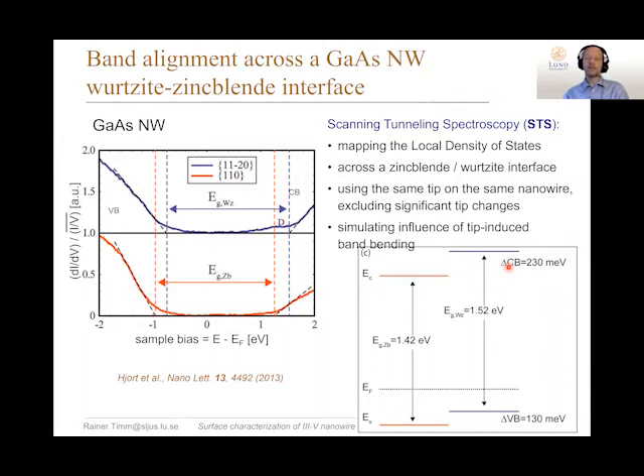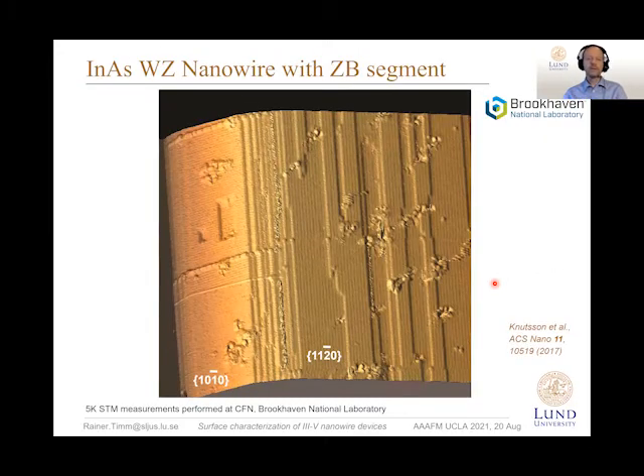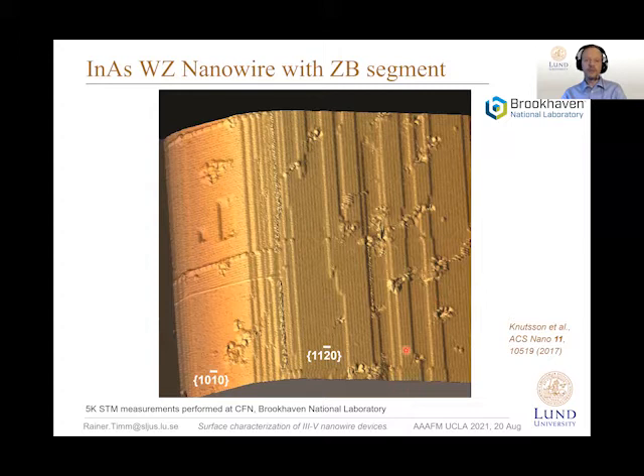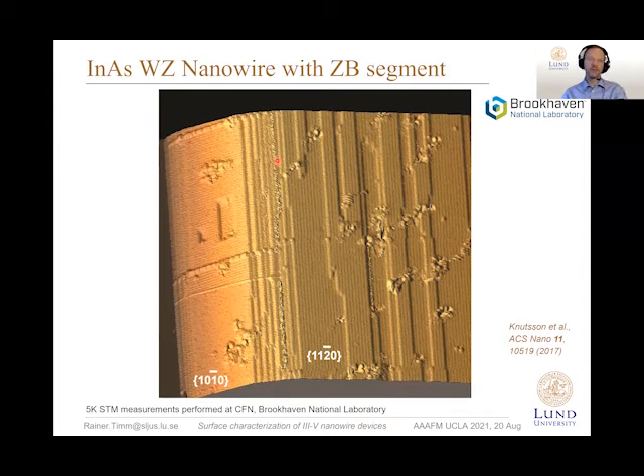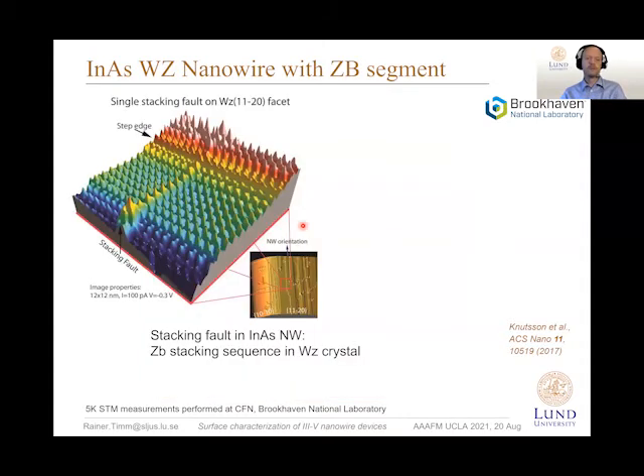That was an example of electronic properties between larger segments. Can we map them even for very small scale segments, very small areas in the nanowire? Here is an example of the smallest possible heterostructure — a side facet surface of a wurtzite InAs nanowire, going again at the 30-degree angle to the side facet. You can see a very thin insertion — this is a stacking fault: a zinc blende stacking arrangement of only around two monolayers within a wurtzite crystal matrix.